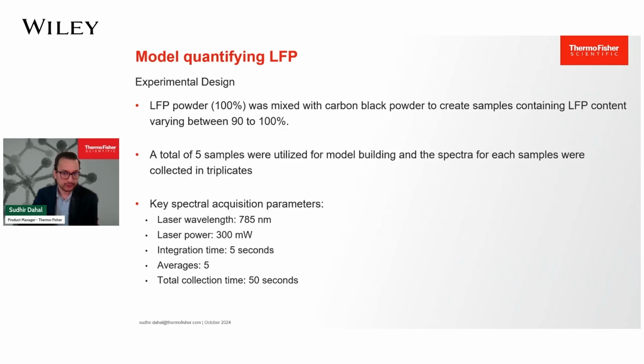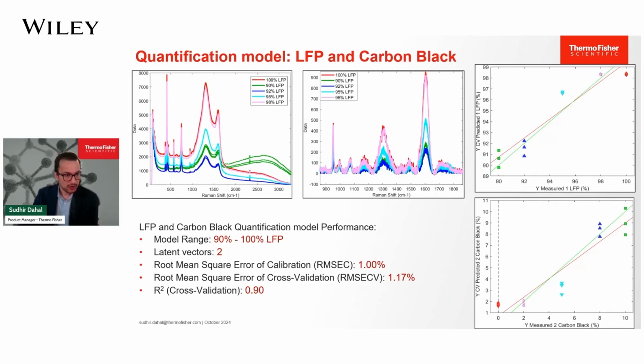This analyzer, equipped with a 785 nanometer laser, was able to rapidly gather spectra and conduct the model in a matter of seconds. The acquisition parameters and conditions are detailed on the slide. As you can see here, and as demonstrated, utilizing this model allows for quantification to be achieved within 50 seconds, underscoring the remarkable efficiency of Raman spectroscopy in terms of time, cost, and resource savings.